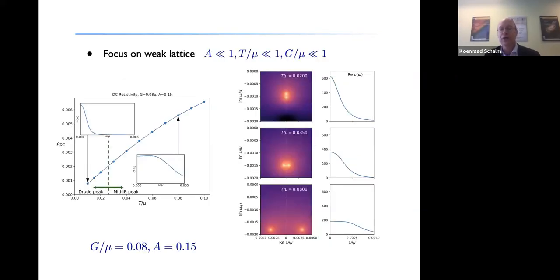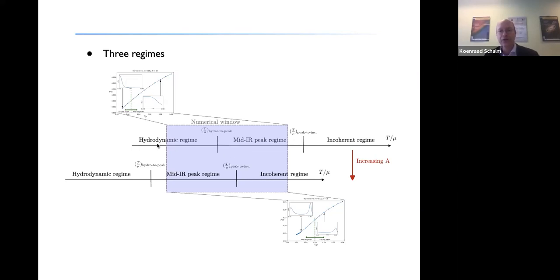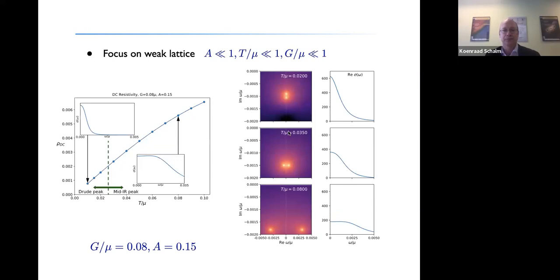So let's focus first on the weak lattice. Let's focus first on this top line here. So I have a small A, and I'm going to discuss this transition from what we call the hydrodynamic regime to the mid-IR peak regime, even though, again, throughout this regime, the resistivity stays essentially linear with the temperature. And one way we can do that is we can very carefully look at the poles in the current Green's function that determine the optical response in the system. And what you see then is the following.